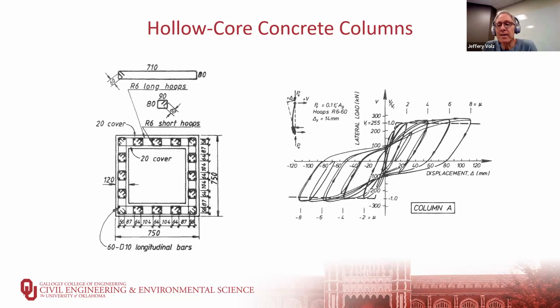One of the important things to notice there is that those values up in the upper right-hand quadrant, that 2, 4, 6, and 8 mu, that is the drift ratio or ductility factor expressed as a percentage. So if you have a 10-foot tall column and it can displace up to 12 inches, then you have a ductility ratio of 10 or 10%. So you can see for this column, it behaves very well in its lateral loading.